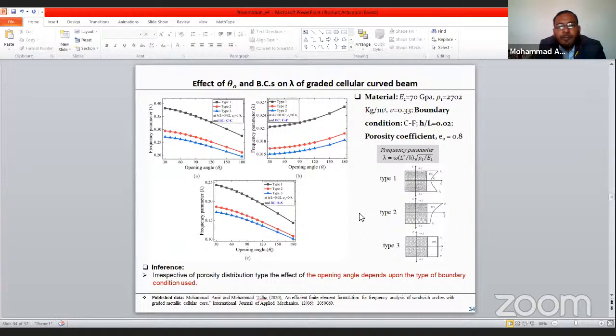Here is the effect of opening angle and boundary conditions on the frequency response of the functionally graded curved beam. The material properties are given here, and the boundary conditions are clamped, clamped free, and simply supported. The thickness to length ratio is 0.02, and E naught, the porosity coefficient, is 0.8. Three different types of porosity distributions are also considered, and the dimensionless frequency parameter is taken as omega L square by H times the square root of rho 1 by E1.